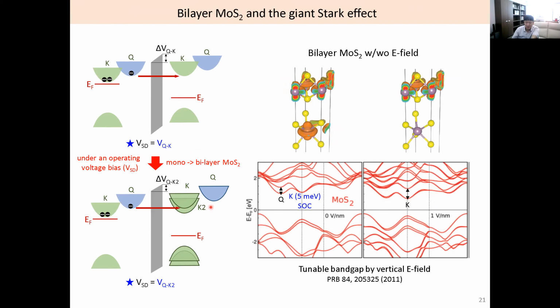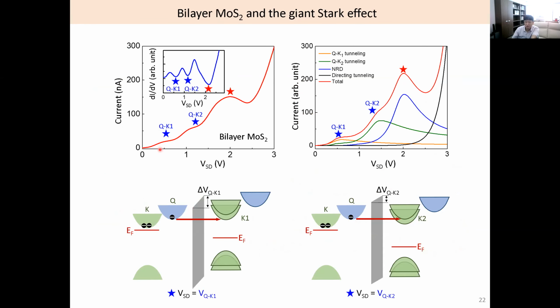So if you apply this Stark effect for our bilayer MoS2 case, if we apply a vertical electric field, the K valley would be split into two states, and we expect some weird tunneling between Q and K. So that's why we have two shoulders for the bilayer MoS2 case, okay, like this.